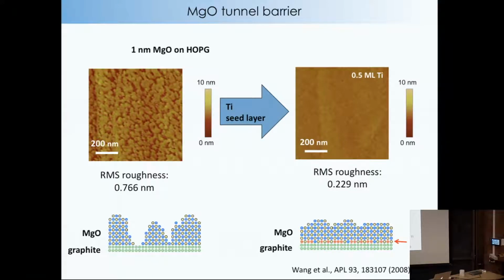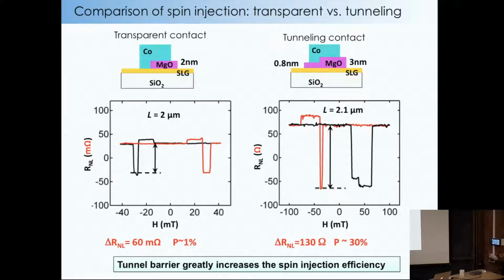And basically what the titanium is doing is inhibiting the diffusion of atoms on the surface. It's like a sticking layer. And then we also oxidize it so that it's an insulator. And then we grow on top, and it's a very nice layer. It took us about a year or so to get this to work, but it does.